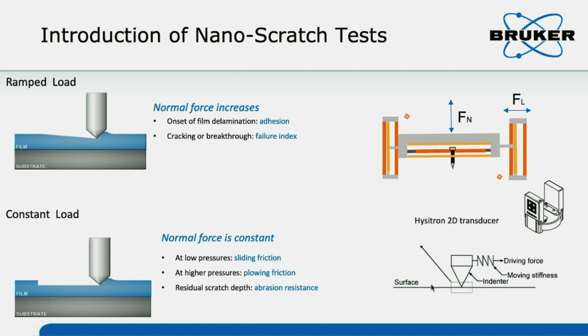So another way is that we use the ramping force. We increase the normal force during the scratch. So that means our normal force will get larger and larger, and when we get almost to the interface, it will cause the thin film delamination. So this is very useful for the thin film adhesion measurement.